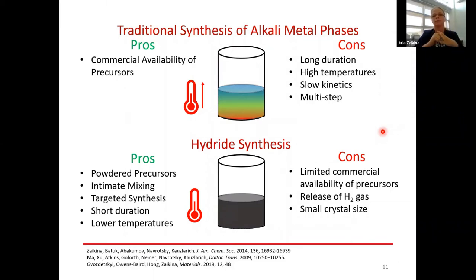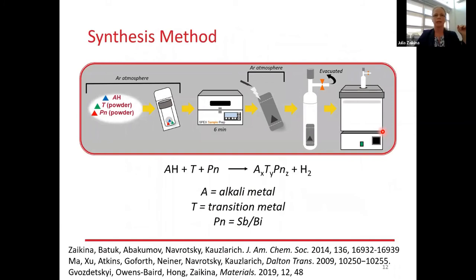And another added feature is that we have the hydrogen gas released, and it's particularly important since we don't want to have even traces of the oxide present. So this allows us to maintain the reducing atmosphere during the synthesis. So this is how we do it.